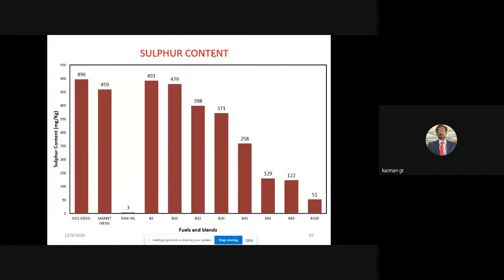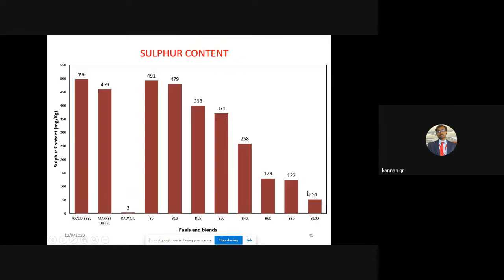For the IOCL diesel, the sulfur content value is 496 milligrams per kg, and market diesel is 459, in milligrams. This is an allowable limit. In the raw oil, that means the palm oil, there's no change, but there may be some error of a small percentage. So we need to properly clean the crucible. If we are not properly cleaning the crucible with solvents, it will give some error, like 51 or 50, but anyway that is within allowable limits.